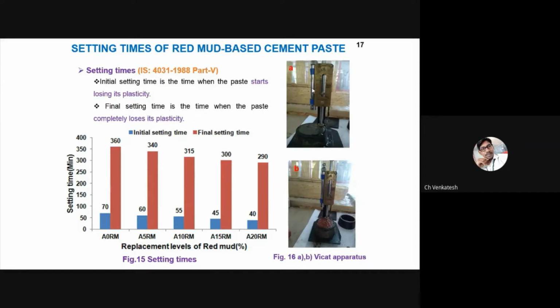IS 4031. The initial setting time should not be less than 30 minutes, and the final setting time should not be greater than 600 minutes. In my study, as the replacement level of red mud increases, the setting time decreases. The reason is that this red mud contains a higher percentage of sodium and aluminate, which accelerate the hardening process. From this result, I can tell you that whenever you are constructing a building or a structure in cold countries, this red mud may be very helpful for the hardening process.